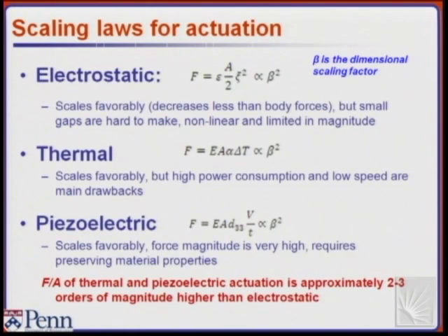If you do F over A, and you calculate for all this type of technology, assuming a few volts of electric field across a 10 nanometer fixed structure, you get 2 to 3 orders of magnitude higher force per unit area out of piezoelectric and thermal with respect to electrostatic. The disadvantage of thermal over piezoelectric is the high power consumption. You always need to flow current through a resistor, whereas electrostatic and piezoelectric essentially use a capacitor, so they don't dissipate energy to move things, right?